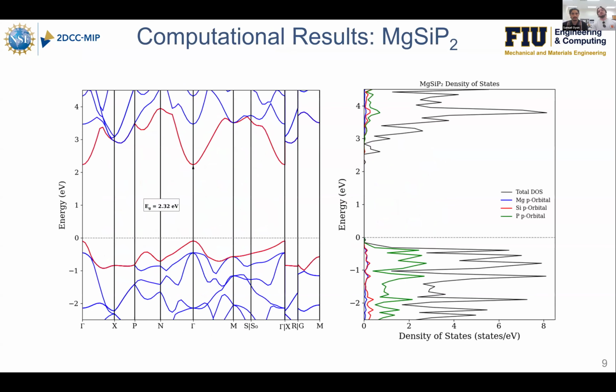But not all was lost. We were still able to simulate a couple of the parent compounds to gain some insight into band structures. Starting here with magnesium silicon phosphide, we have here on the left the band structure. You can see, comparing to literature, the direct nature of the band gap is recreated here in the simulation, with the band gap of 2.33 eV from literature almost exactly replicated here, 2.32 eV at the gamma point in the Brillouin zone.